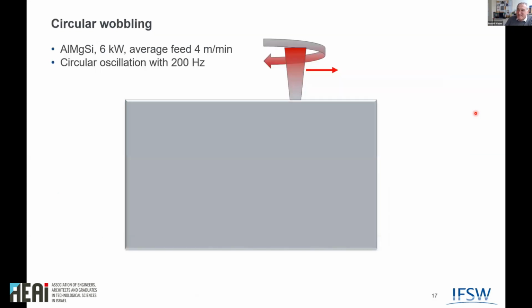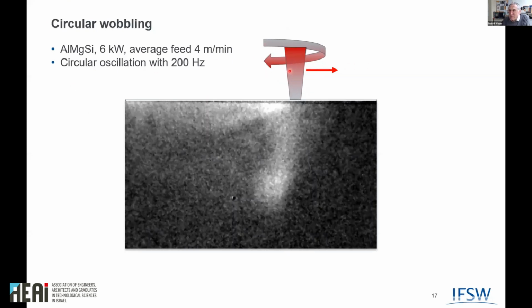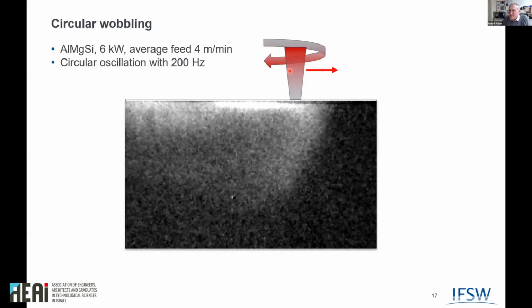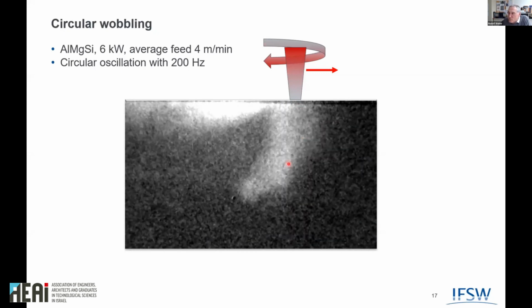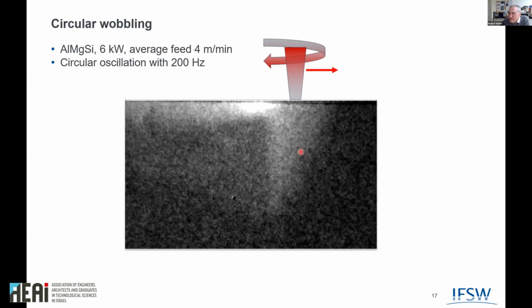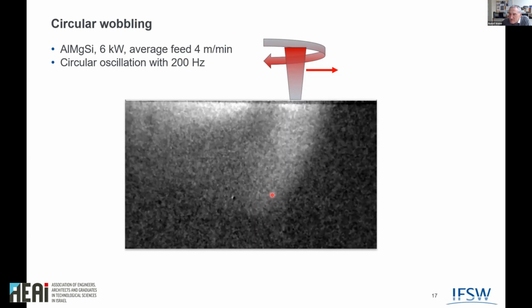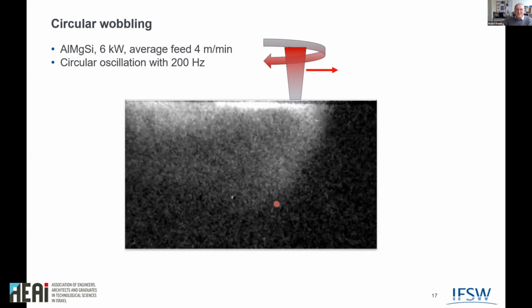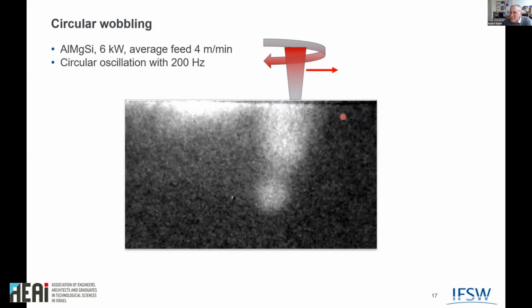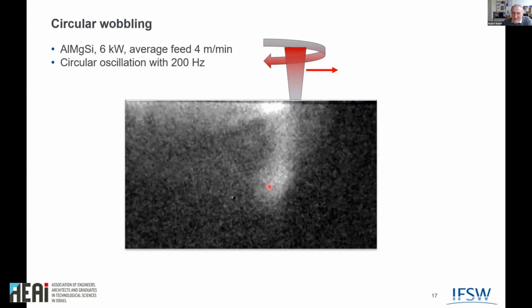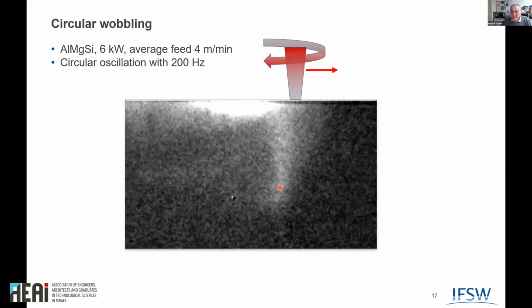However, the nice thing is, another possibility is some circular wobbling. You just move the beam around. That's how it looks. These are the parameters again. 200 Hertz was nice. And that's how it looks inside the weld then. What you can see is that the capillary is moving around. This is the capillary here. And at a certain point, a pore is created. And after the next round, you see that the capillary is coming back and eats up the pore again.